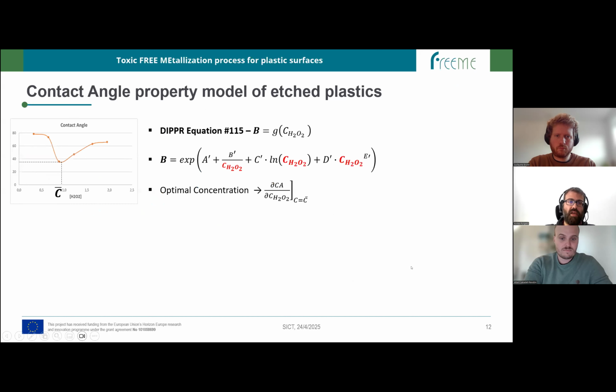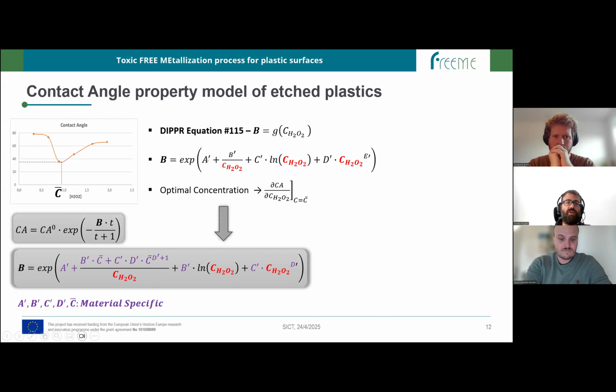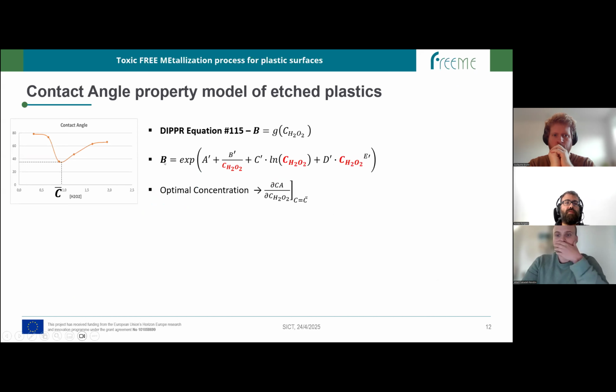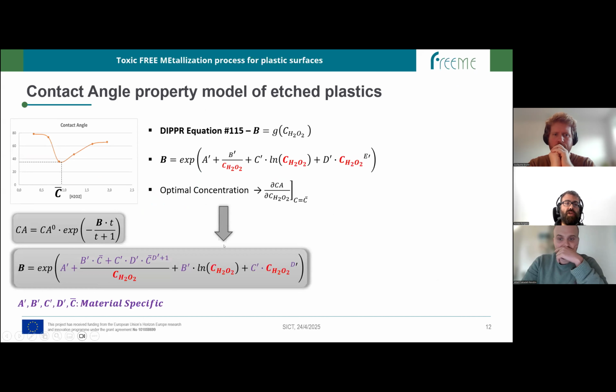So going further and in order to introduce the hydrogen peroxide effect, here you can also see that there is an optimal concentration where the contact angle could be minimum for different cases. And we have been again inspired by a DIPPR equation, and we have accordingly developed a model for the estimation of the parameter of the model affected by the hydrogen peroxide concentration. And here comes the whole model, where the contact angle is estimated versus time and versus hydrogen peroxide concentration, where parameters are also included, which are material specific.